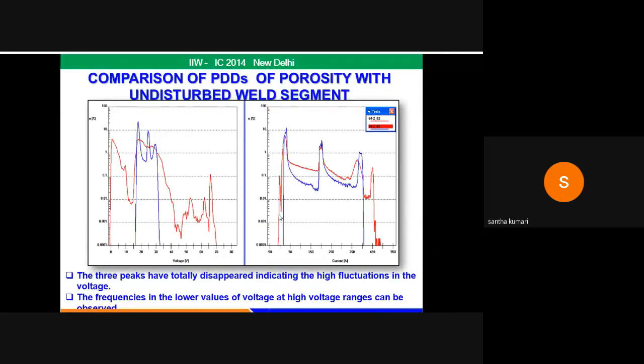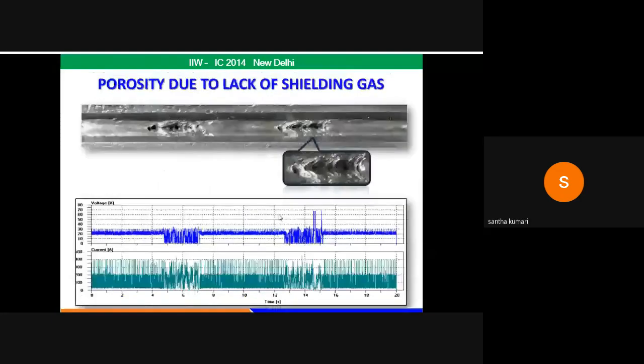I'll show you another example. In the second set of experiments on porosity, we controlled the shielding gas. We cut the shielding gas for about 6 seconds, then allowed the shielding gas, and then cut it again for 3 seconds. You can see this exactly in the timeline of the transient. So two porosities were created with this trial, and the pores are shown here with the transient signals.